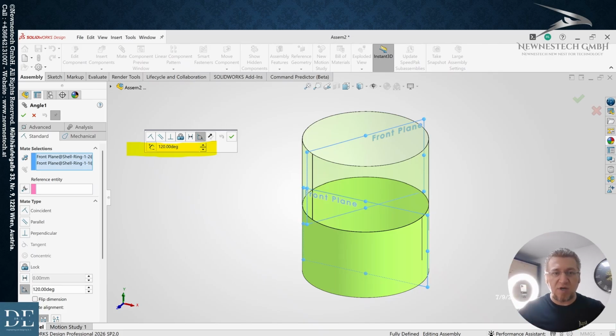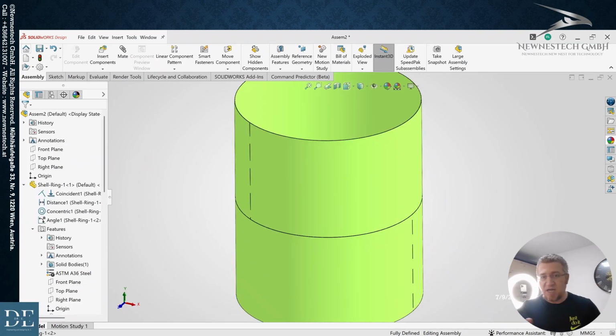As you see, I am considering a 120 degree angle between the front plate of the second ring and the front plate of the base ring. With this consideration, we need to have a 1.5 millimeter distance between two meeting rings for the penetration of the root welding. To do so, we are considering a 1.5 millimeter distance between the top plane of two successive rings, first and the second. Perfect. This is how it will look like after just assembling two pieces of rings together.